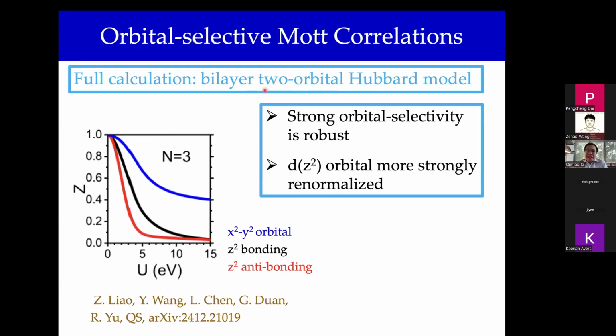So the 3dz square and 3dx square minus y square orbitals per nickel, and so there are 2 nickel and therefore 4 orbitals. And we allow all the 4 orbitals to be in the mix, and in addition to general characterization, there's some particular motivation of comparing with experiments, and I'll come to that shortly. But this is the result of calculation for n equals 3, 3 electrons occupying these 2 sets of d orbitals.